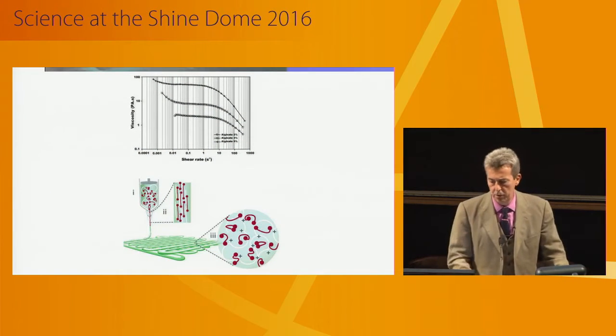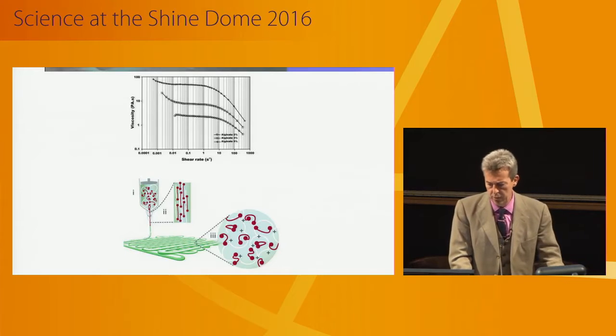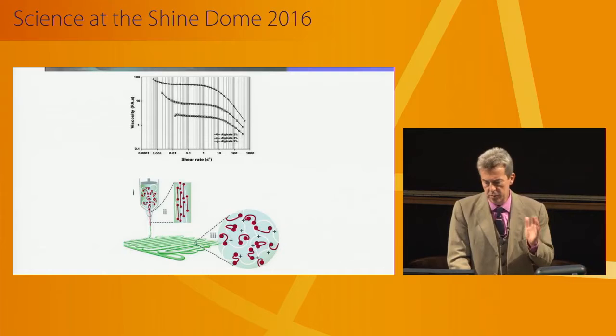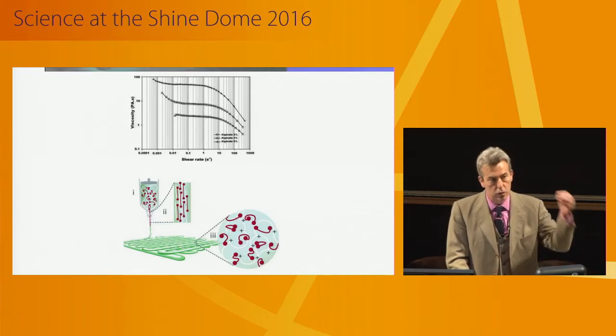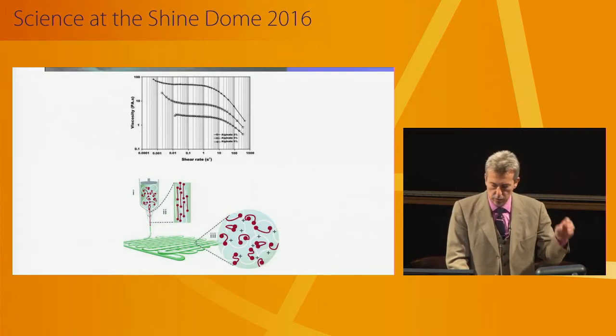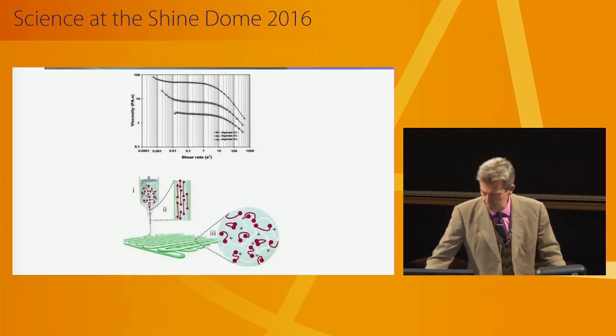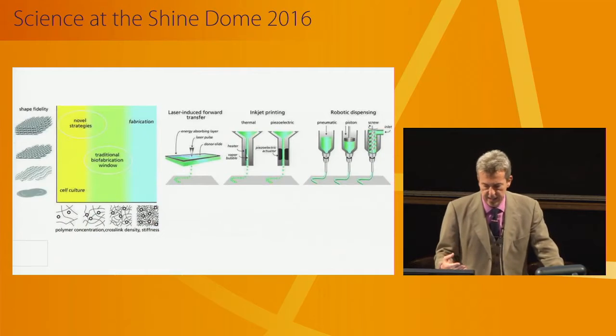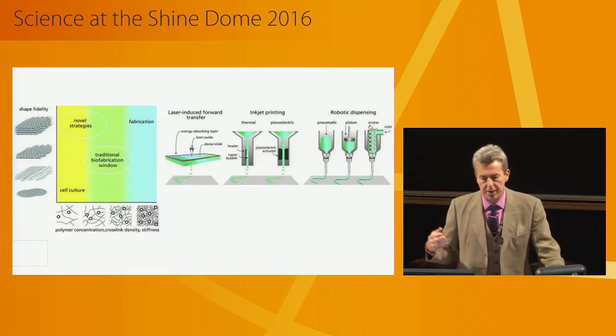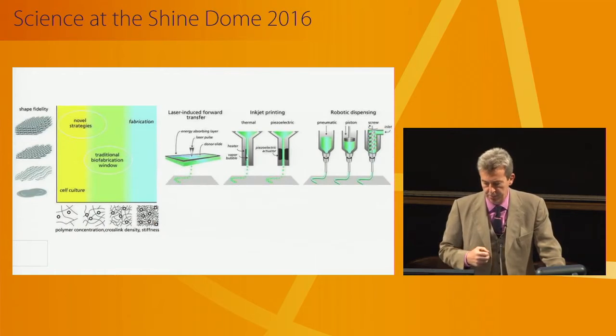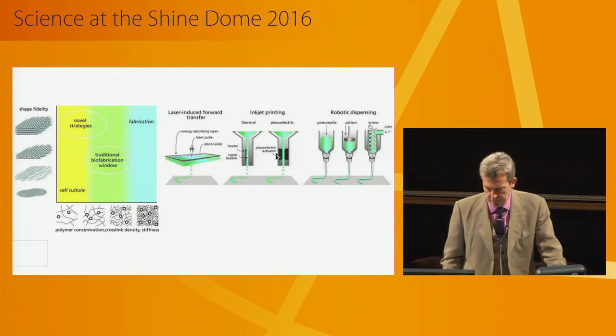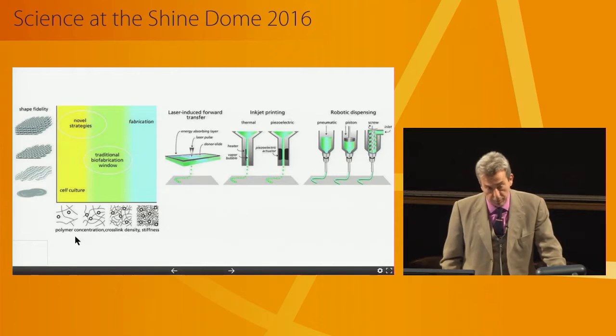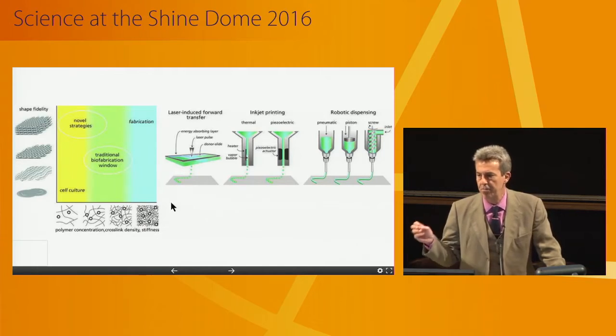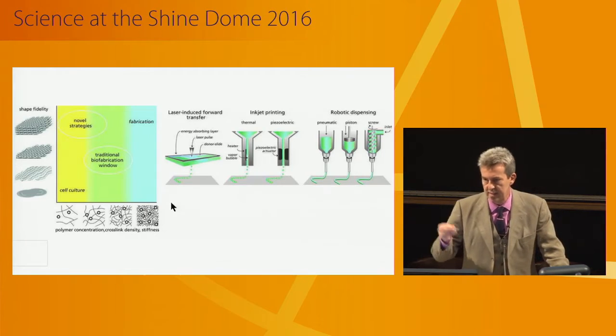So again, one side of 3D printing is that we have to develop what we call these bioinks, where we really look from a technology and material science point of view, what is the best way to really print now these biomaterials, to have high spatial resolution, shape fidelity, and so on. But one of the challenges we are facing is, if we want to have something which is able to do that, for example, we are looking at mechanical properties, that we have shape fidelity. So this is normally done in the chemistry, as you see down here, where we can play around with a polymer, with the molecular weight, the concentrations, the cross-linking density, and the stiffness. But specifically, if we change the cross-linking density and stiffness, this has a major effect on the cells, and that effect is negative. Our cells cannot proliferate anymore.